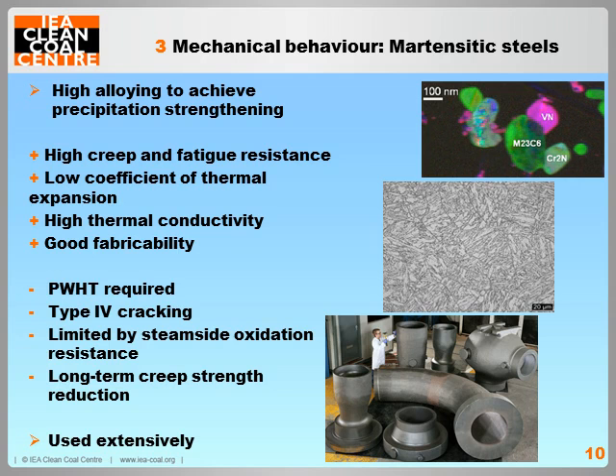of up to 25 megapascals, but they are limited by the resistance to steam side oxidation. 11 to 12% chromium martensitic steels can operate up to 620 degrees Celsius at low pressures of less than 10 megapascals, but are limited by their strength. Martensitic steels do, however, require expensive and time-consuming post-weld heat treatment. They suffer from long-term weakening mechanisms and they are susceptible to cracking.